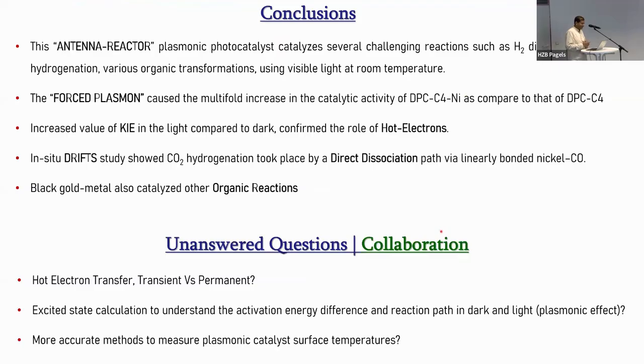Right, with that, I'd like to conclude. I showed you the concept of plasmonic catalyst, the black gold, and I showed you that black gold, although it harvests lots of solar photons, the lifetime of the electrons was poor. We created this antenna-reactor system where black gold acts as an antenna, takes all the photons, and gives them to the reactor, which is nickel, and it gives you a very good CO2 conversion. And that's where the term forced plasmon came in, because nickel is not plasmonic in the visible range at that particular particle size. But now you're forcing it to behave like a plasmonic material because of the black gold and the electric field around it.